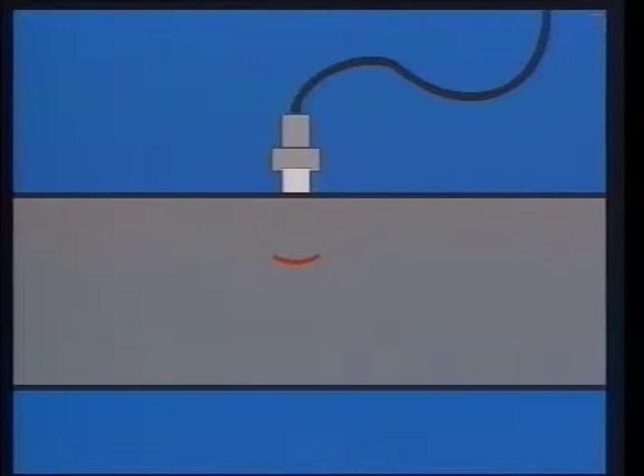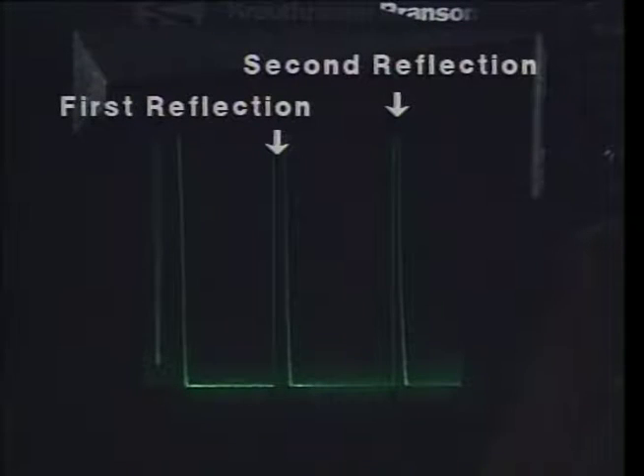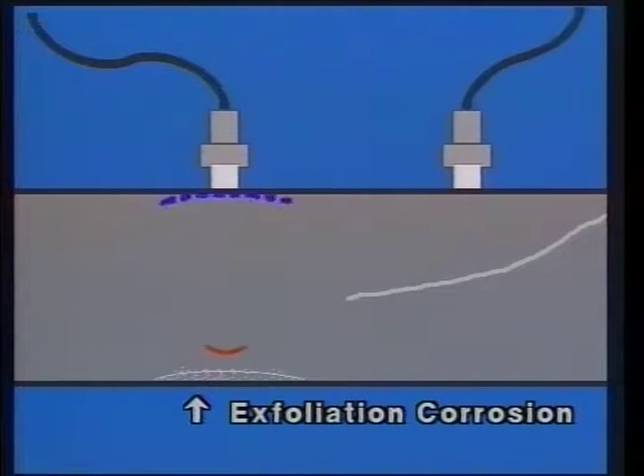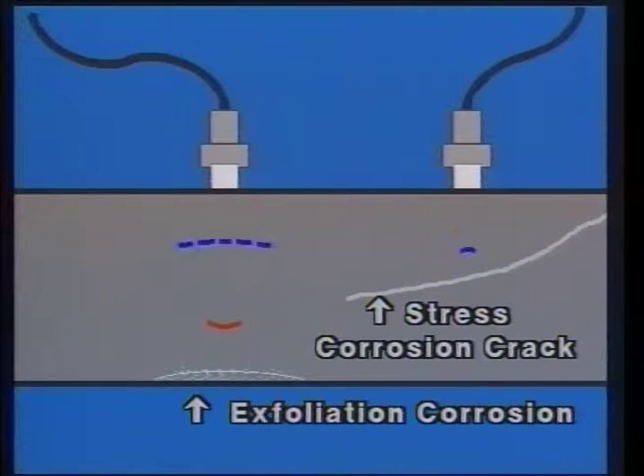Basically, the sound pulse travels into the bulk of the material under test until an echo is reflected by the back surface. This CRT display shows good calibration, for the times between echo spikes from the back surface are equal and linear. If the material has been thinned by exfoliation corrosion, this new surface causes echoes to return in a shorter time. Similarly, a stress corrosion crack within the material creates an echo return sooner than the calibrated back surface.